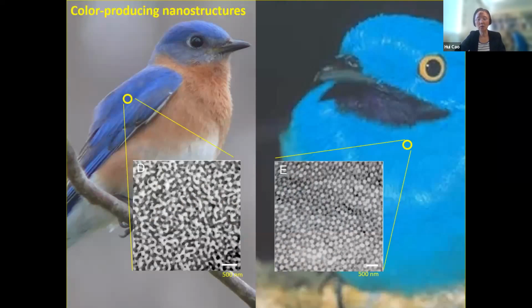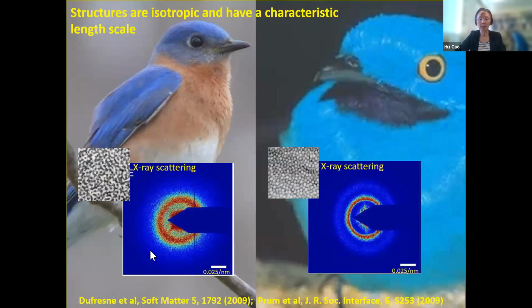So how did he know Raman was right? Because he tried to do the spatial Fourier transform of these structures, taken by the electron microscope. And then he realized the structure is not completely random. There is some order in there. So later on, they did so-called X-ray scattering. X-ray scattering is more like doing the physical Fourier transform of a structure. So here you can see this pattern, and we see a ring. Part of the ring is blocked by this beam block. But it is a ring, so it is isotropic.